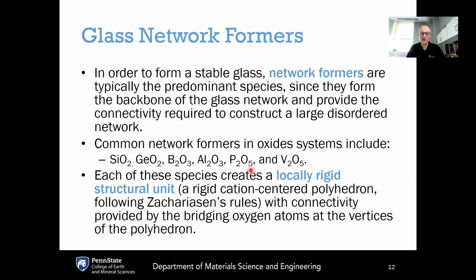Phosphate also forms tetrahedral units, and we're going to see in chapter 5 exactly how that works, but phosphates also satisfy Zachariasen's rules, as do vanadates, and we're going to come back to that in chapter 5. In each of these cases, each one of these network formers creates a locally rigid structural unit. So either a tetrahedron or a triangular unit where that unit itself is locally rigid, meaning that the atoms do not have degrees of freedom that can perturb the structure of the tetrahedral unit itself. And this rigid cation-centered polyhedron follows Zachariasen's rules, and then the connectivity provided by the bridging oxygen atoms at the vertices of the polyhedron is what enables these polyhedra to link together.